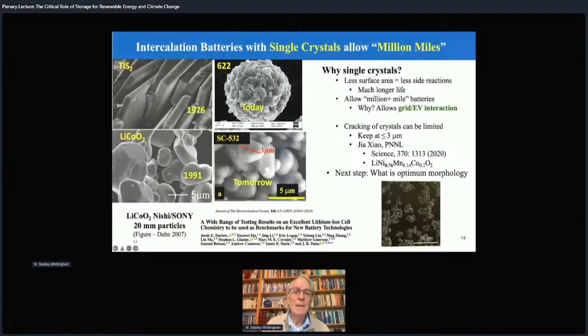But to increase the power, commercial cells today have these meatballs, much smaller particles. The primary particles are 100 to 200 nanometers. The large particles about 10 microns. So fairly large surface area. So what they're thinking is, if we go back to single crystals, yes, we'll lose some of the rate capability, but we'll have much longer lived. So Jeff Dahn made this 50% nickel material and speculated that it could last for 1 million miles. And I say you need this to allow grid EV interaction.